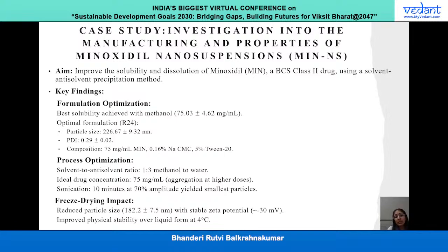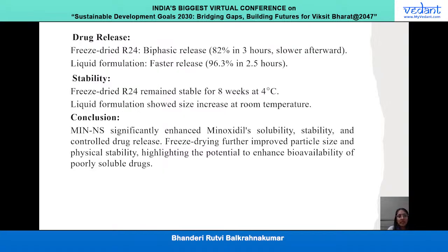Process optimization: solvent to anti-solvent ratio 1:3 methanol to water. Ideal concentration 75 milligram per milliliter. Aggregation at the higher doses, sonication for 10 minutes. Freeze drying impact: reduced particle size with stable zeta potential, improved physical stability over the liquid form at 4 degrees Celsius. Drug release: they have shown freeze dried R24 has biphasic release, and the liquid formulation has shown faster release.